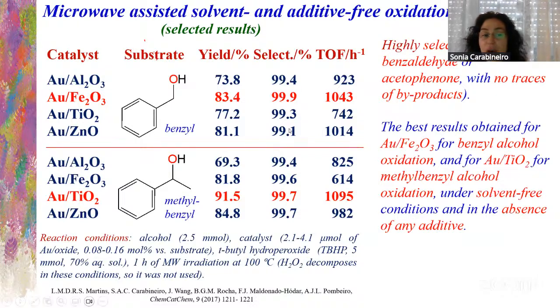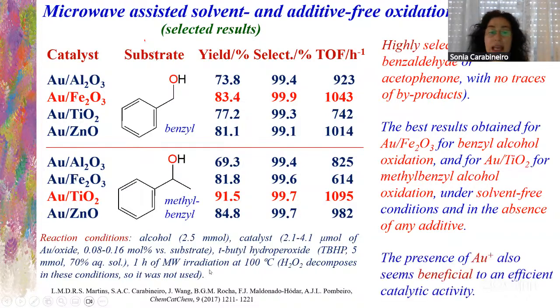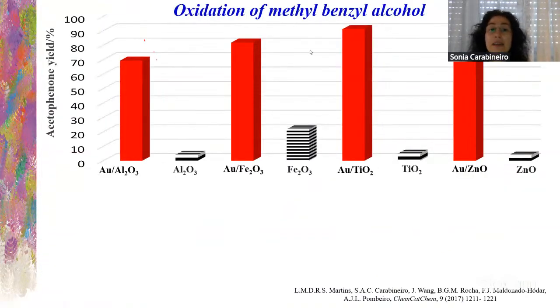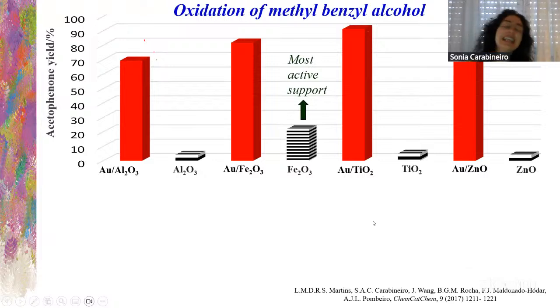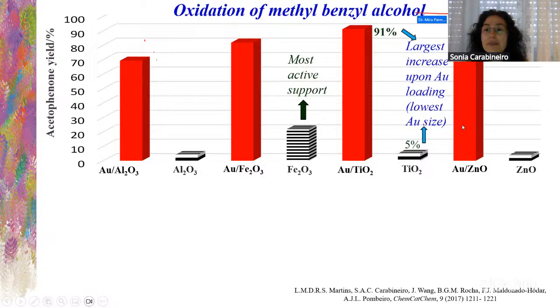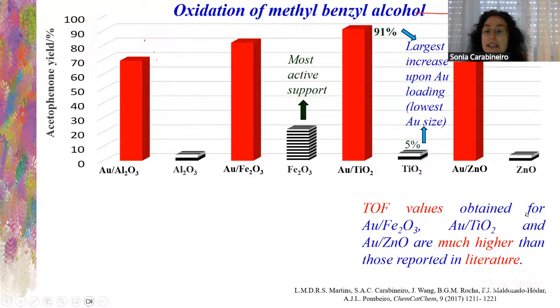For methyl benzyl alcohol, it was titanium dioxide as support for gold. And we see that the presence of gold plus also seems to be beneficial for catalytic activity. Here is a comparison of this oxidation of methyl benzyl alcohol, with supports without gold and with gold. We see adding gold is, of course, much better. Iron oxide was the most active support. That's not surprising because it was the most reducible one, as we saw. However, the largest increase upon gold loading is obtained with titanium dioxide. The turnover frequency values obtained are much higher than those reported in the literature.